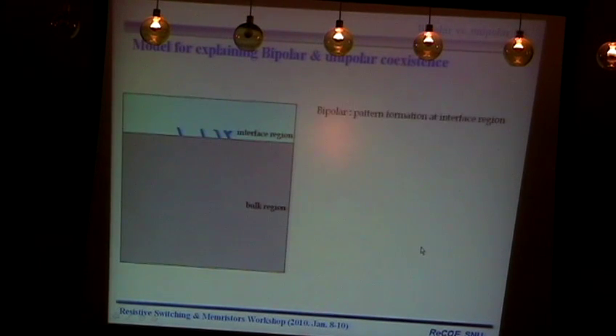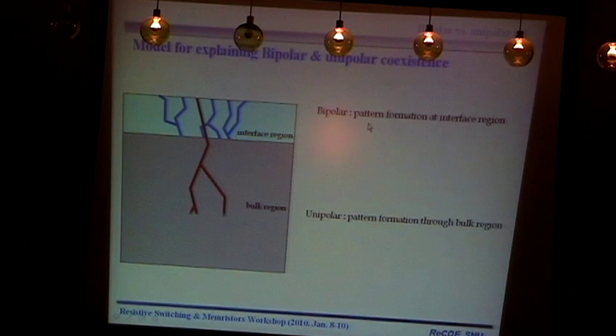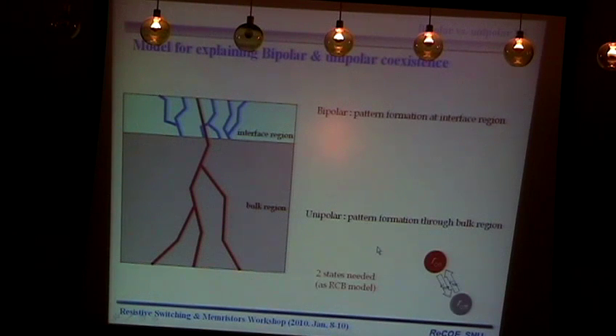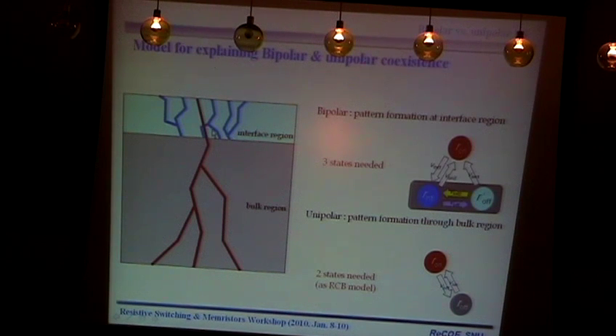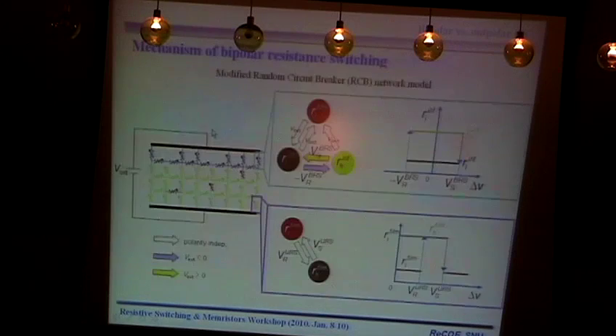So the simulation we have to modify in such a way that in the interfacial region, we probably have a bipolar switching from the pattern formation at the interface, but the unipolar is coming through this pattern formation through the bulk. But in here, the unipolar, we just use the two state. By bipolar, as shown in this column, we need at least three states. So simulation is a little more complicated. However, we can do the simulation. So we just have a three state at the interface.